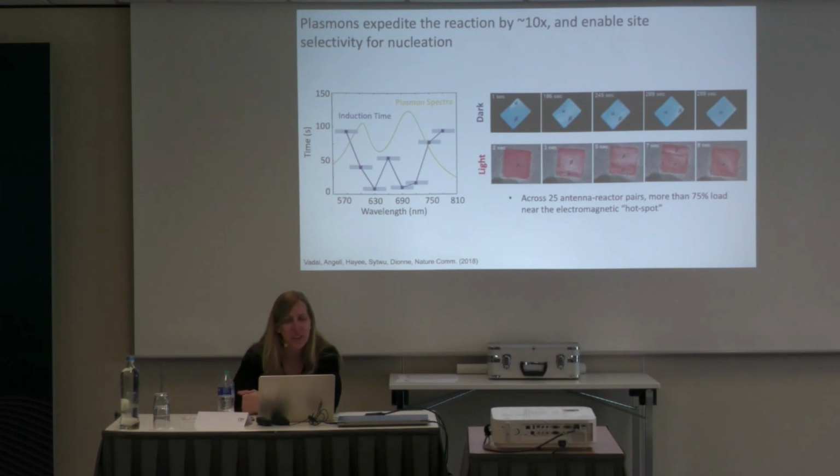Yeah, great question. So in this case, yep, the plasmon spectra is a combination of absorption and scattering, right? So this is kind of your extinction resonance. So there is some local heating. When people have tried to determine the heating through a combination of computational and experimental approaches, they found that very likely the heating is not more than a few degrees. So that's not enough basically to cause a substantial change in the diffusion.